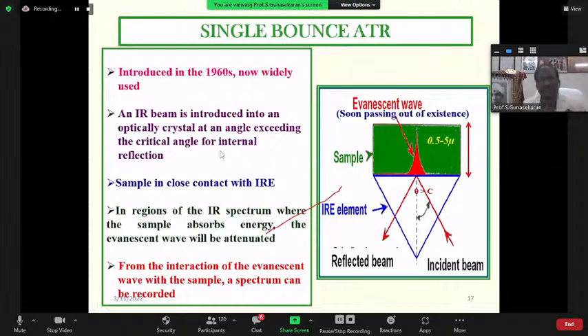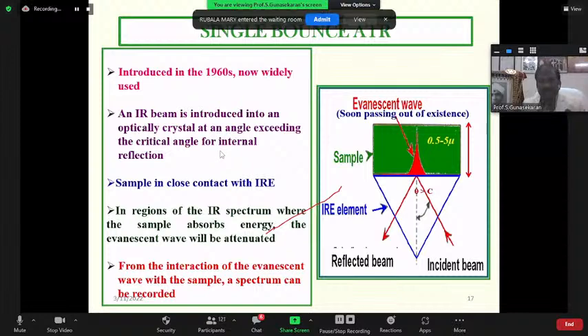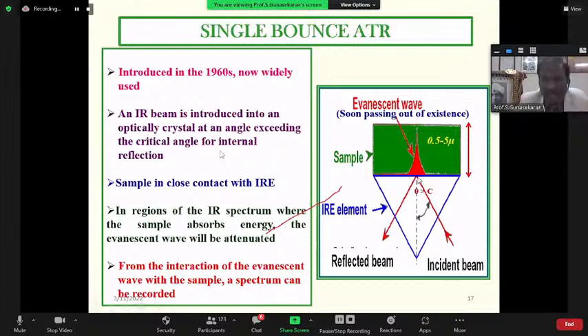At the point of incidence, the angle of incidence is adjusted so that theta is greater than the critical angle, so that we can get the total internal reflection and the reflected wave. At the point of incidence, an evanescent wave is produced above the crystal, extending into the sample for a height of nearly minimum 0.5, maximum 5 micron, 10 power minus 6 meters.